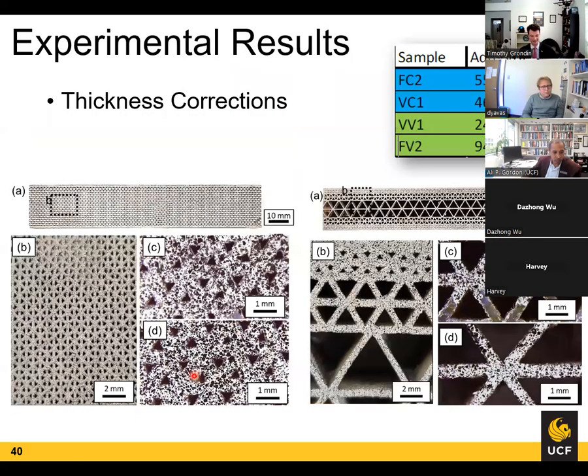Initially, we were a little let down with our results. We're showing an original 94% performance factor ratio. So we took everything, literally put it under a microscope. We took some fine, expensive calipers and did some measurements. It was found that the strut thickness in the lower density regions averaged out to our anticipated 0.02 inches. However, the strut thickness in the entire constant density sample, as well as our highest density layer by the face sheet, was 0.028 inches, which is almost an increase of 40%.